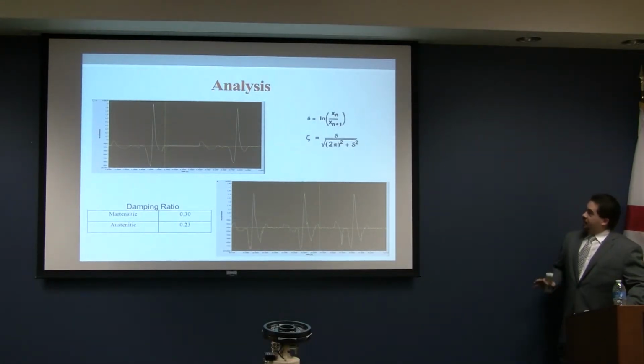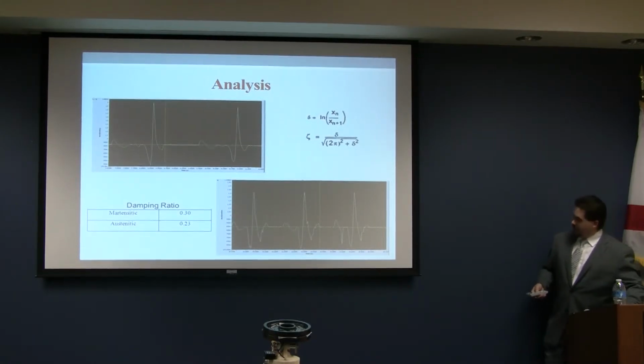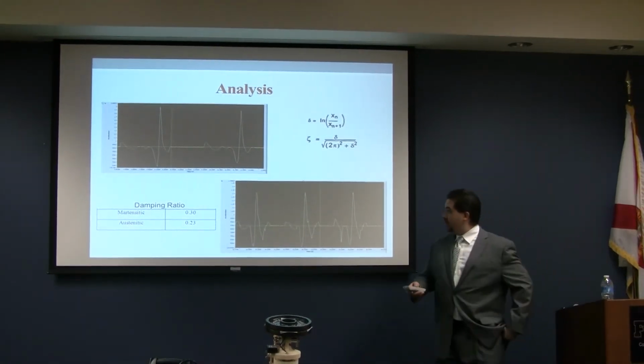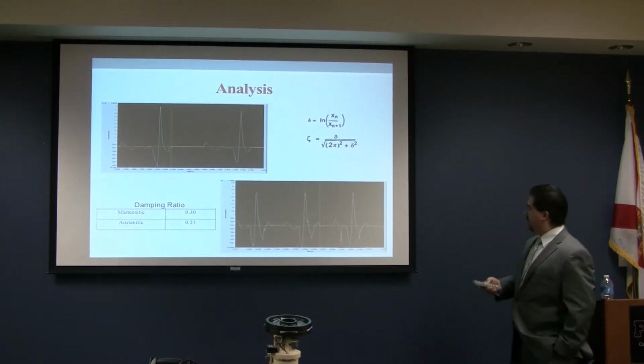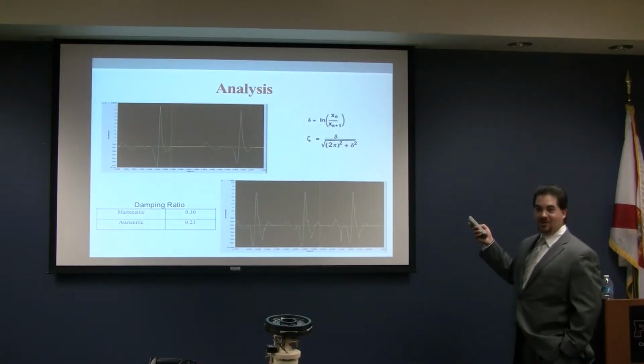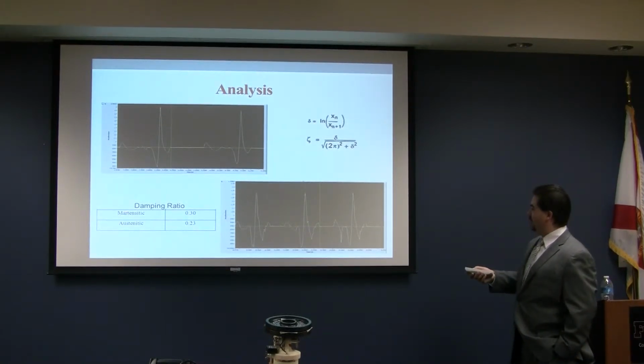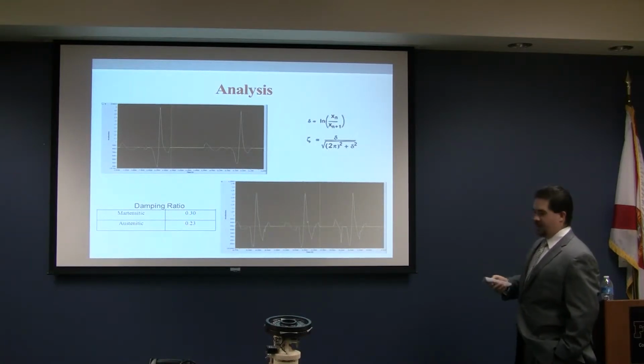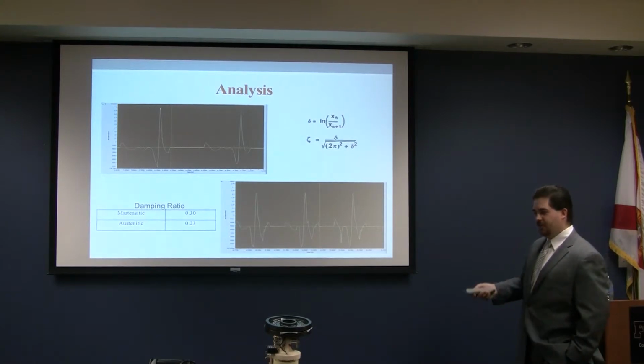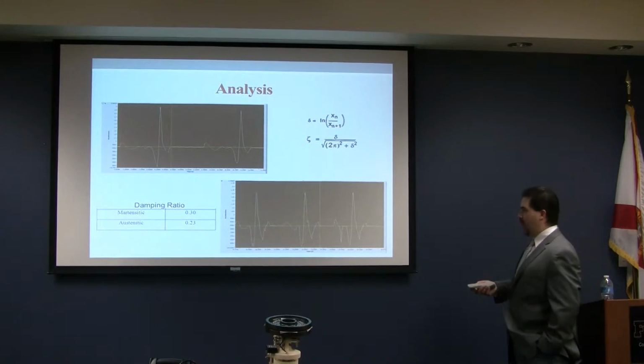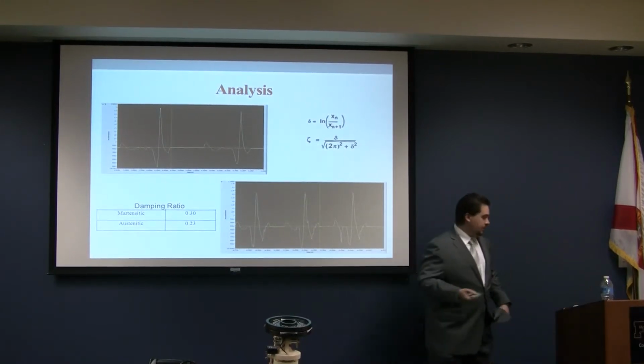This is some of the analysis that we were able to capture using the 3-axis accelerometer, based on our system dynamics calculations here, which a lot of this should be familiar to some of you guys. The damping ratio for the martensitic state was 0.38, and the austenitic state was 0.23. Now, based on some of the friction and other variables that we can't account for, we believe there's some drop in it that's really nominal, but it's not accounted for here.